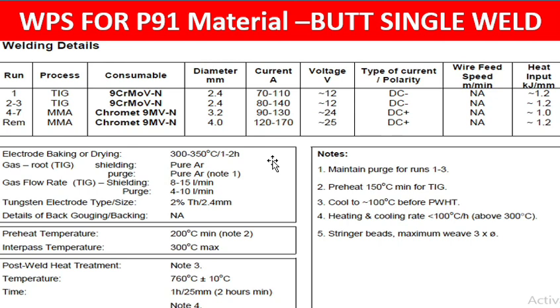The Chromet 9MV-N. For this MMA, we are using two types of diameter: one is 3.2 and the last one is 4.0, that is capping. For 3.2 we are using 90 to 130 current, and 4.0 uses 120 to 170. Based on the manufacturer recommendation, we are using this current.